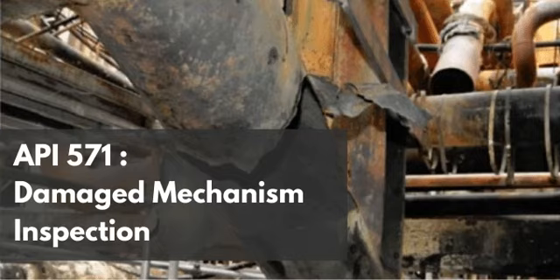When a circumferential pipe weld is deposited, the localized area is elevated to the melting point of the steel. Right, obviously. But as the weld pool solidifies and cools down to ambient temperature, the metal undergoes severe volumetric shrinkage. It shrinks as it cools. Exactly. But that cooling weld is physically restrained by the colder, solid pipe on either side of it. It cannot shrink freely. So it's basically locked in a tug-of-war. Precisely. And as a result, massive tensile residual stresses are locked right into the metallic matrix.